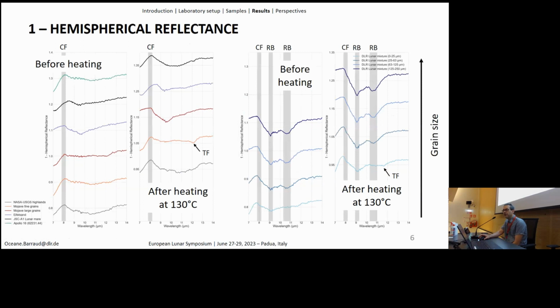So before and after heating, you will see that there are some trends. Most of the time, we have a shift in the Christiansen feature, and this is not constant. There are some examples where the shift is going to the lower wavelength ranges and sometimes to the larger wavelength ranges. But something that you can notice is the Reststrahlen bands after heating. So this is again hemispherical, so taken at room temperature on the sample fresh or after heating, but in any case it's everything at room temperature. You can see that Reststrahlen bands increase a little bit in the contrast. So this is an important factor.